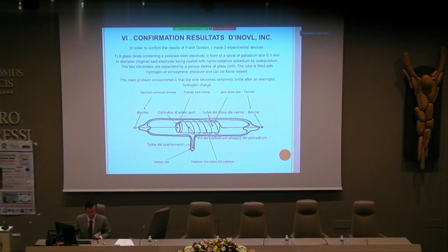So I tried to confirm and reproduce the result. I built 3 devices. First, a device totally sealed in glass with a polished cylinder of steel and a little wire of palladium covered by electrodeposition with nanometric palladium.